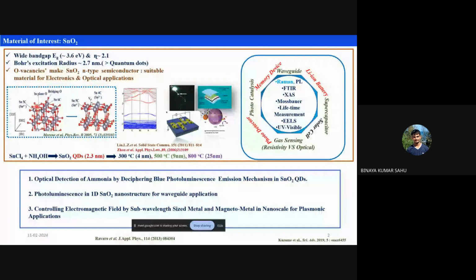Here we can see this is a plane and this is a plane, and a few oxygen are bridging these two planes. These oxygen that are bridging the two planes are known as the bridging oxygen, whereas the oxygen lying on the plane are known as the in-plane oxygen. But if you remove this oxygen or this oxygen, they will create a certain kind of oxygen vacancy. Because of the oxygen vacancy, certain energy states will be created below the conduction band. We are very familiar with this kind of structure: if you create a donor state closer to the conduction band, it behaves as an N-type semiconductor.